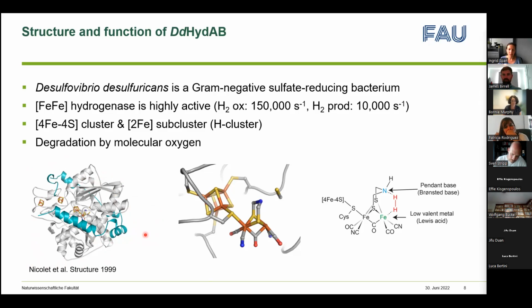If we look at the active site, it's buried deeply into the heart of the enzyme, and we have the so-called H cluster that consists of a cubane-type 4-iron-4-sulfur cluster that is coordinated by 4 cysteines, and one of the cysteines is bridged to the 2-iron subcluster that also contains carbon monoxide and cyanide ligands and an ADT bridge. In addition to the H cluster in the active site, we have 2 4-iron-4-sulfur clusters that are called the F clusters. They're responsible for efficient electron transfer to the active site.